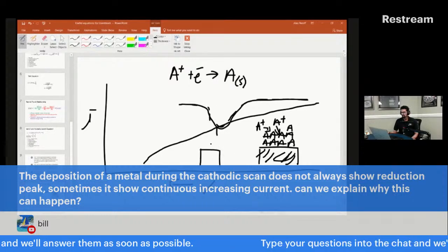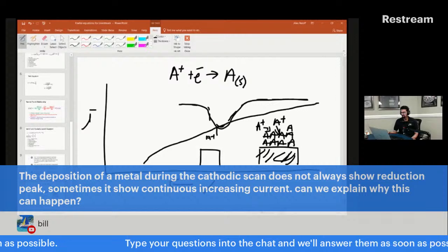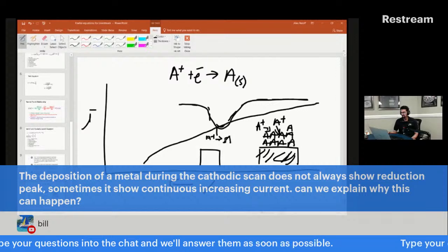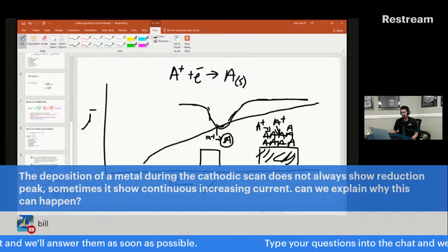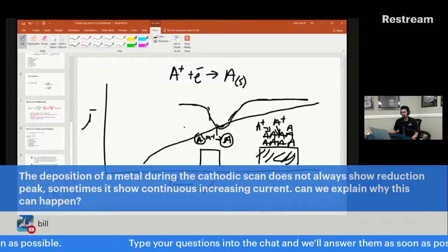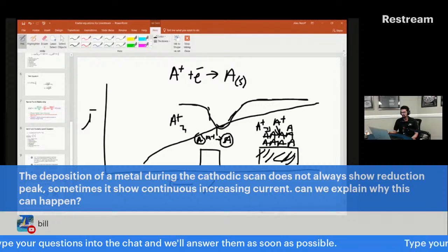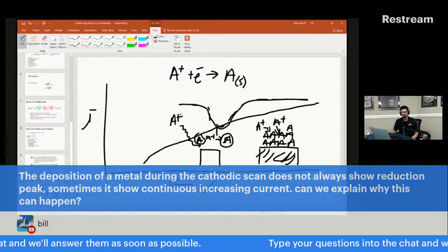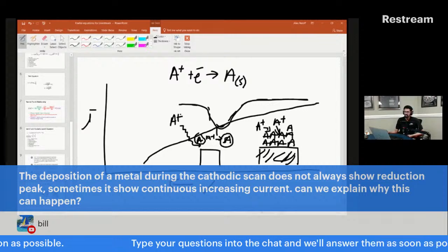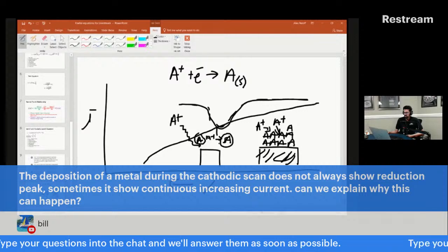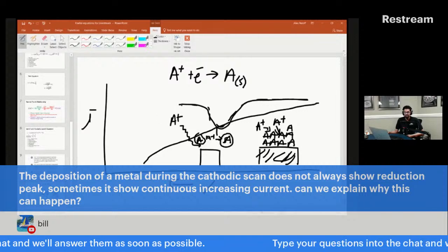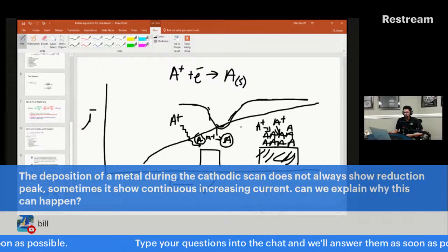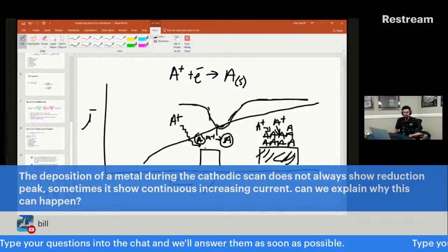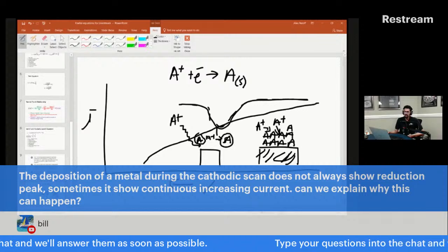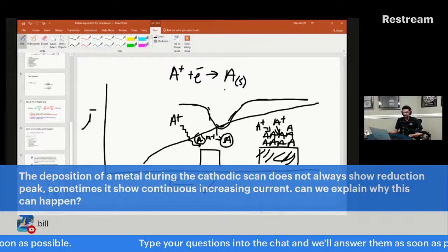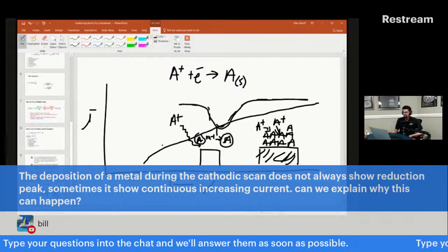When you have a traditional peak, once you have converted A plus going to A, there's A that just hangs out in solution, and you're waiting for diffusion of an A plus to make its way to the surface. That's the thing that makes it so that this doesn't go up forever, but actually drops, because it takes longer for an A plus that's further out from the diffusion layer to make it towards the electrode surface. So that may be one reason why you're not observing a peak.